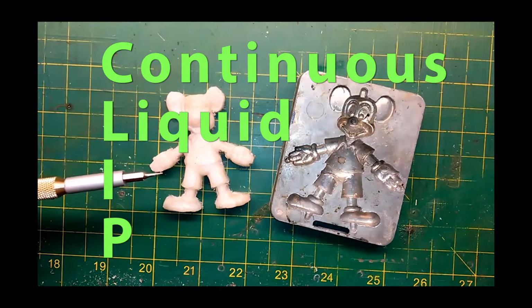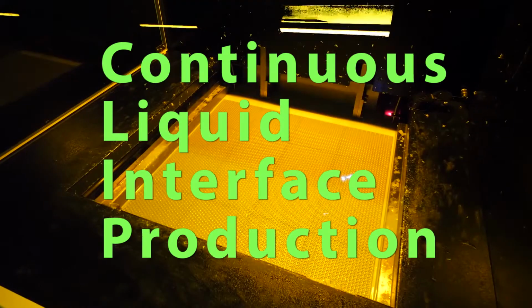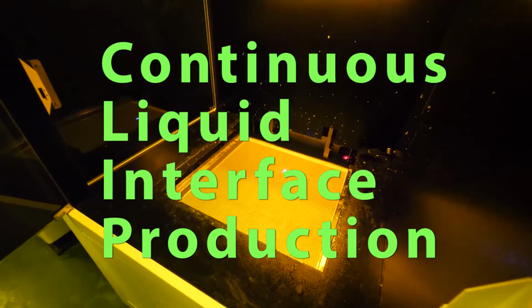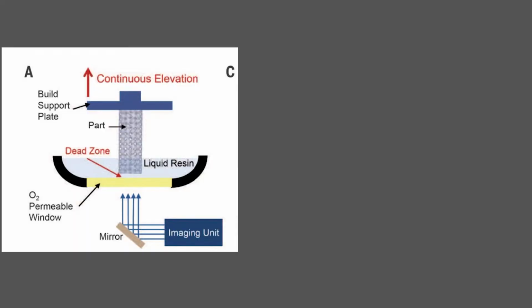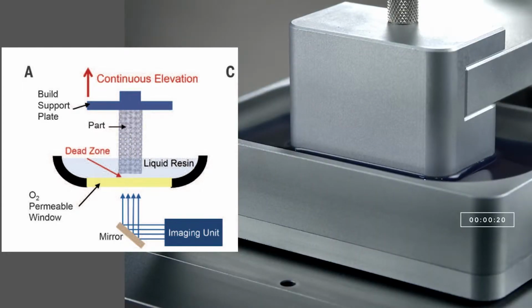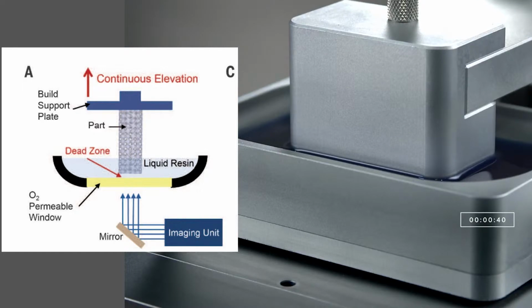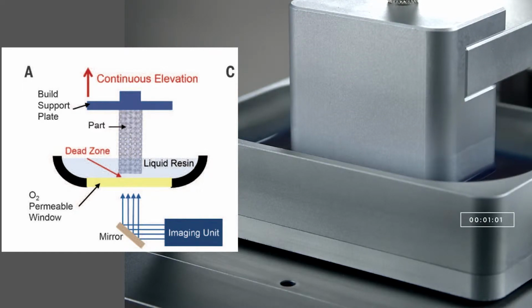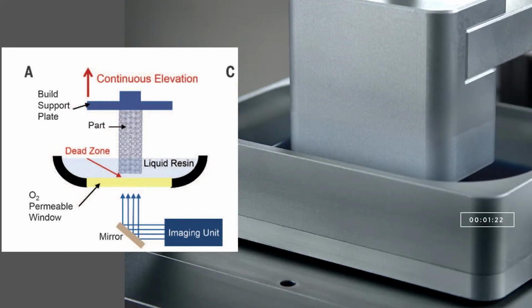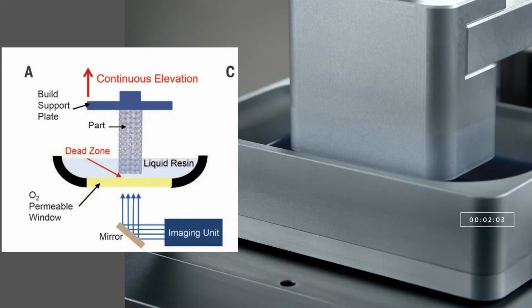CLIP, continuous liquid interface production, is one such technique and our topic today. CLIP is set up like this. A platform is submerged into a solution of monomer. A window below allows UV light to pass from a laser or screen into the solution. Where the light shines, the resin hardens, forming plastic that adheres to the platform, which grows a structure controlled by light. By letting a computer carefully control the UV exposure, a dynamic shape can be printed.